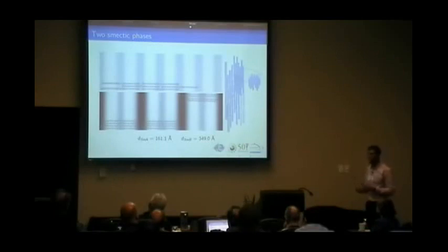But we did also Monte Carlo simulations, and what we found out is that those two structures probably are not possible. The most energetically probable structure is the folded model, which is here. And we did not expect this behavior.